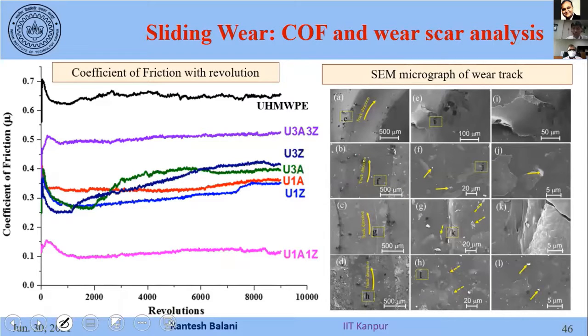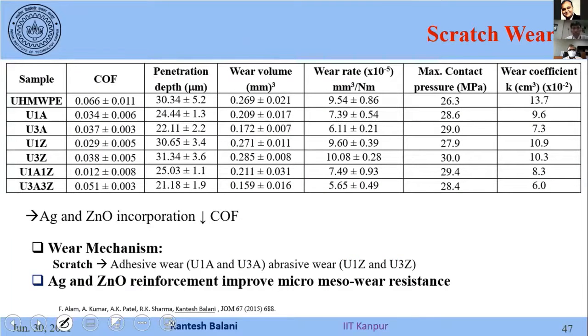And again, we go to an even higher length scale. We have done pin on disc, and pin on disc brings out the real response. Here I see that 1A 1Z is coming out with the least coefficient of friction. That's why I was saying that we should prefer this. If we get more antibacterial response, it also has higher friction with respect to the surrounding. Though it is giving a low wear rate, I'll still recommend going for 1A 1Z because it has the right amount of silver and the right amount of zinc oxide. Higher silver is also not good. It starts to lower the cytocompatible response. We have also seen for the hydroxyapatite system that higher silver content lowers the cytocompatibility. So higher silver content is not good.